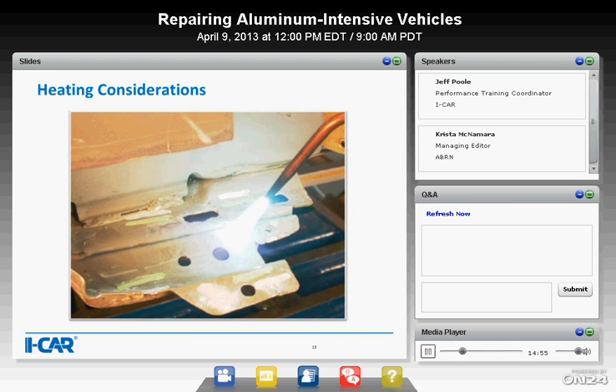Minor damage to stampings and extrusions may be repairable cold. The work hardening, though, is the thing that we're kind of challenged by. And what we know is that using heat within reasonable limitations, reasonable guidelines, can assist in allowing us to move those molecules back where they should be and reduce the tendency to crack. No guarantees here, but it is something that will help increase your chances of success.